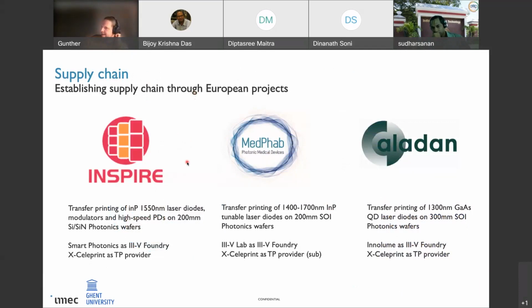This is currently carried out in the context of 3 European projects, one using Smart Photonics as a III-V foundry, where we are printing indium phosphide C-band devices. One where III-V Lab is the III-V foundry, where we are also printing indium phosphide devices in the 1400 to 1700 nanometer wavelength range. And one project where we work with Innolume as a III-V foundry to transfer print gallium arsenide quantum dot SOAs or lasers on silicon photonics.